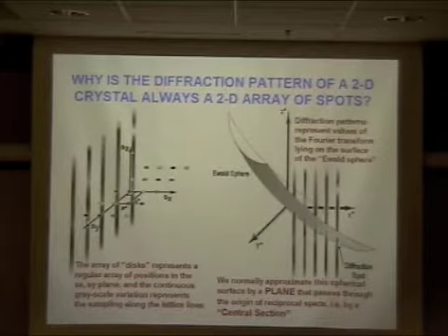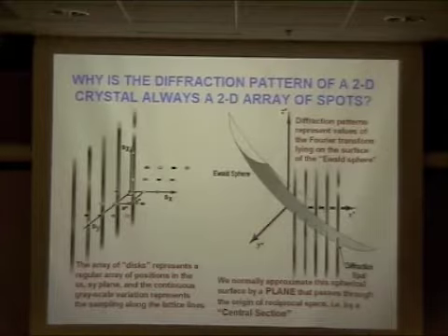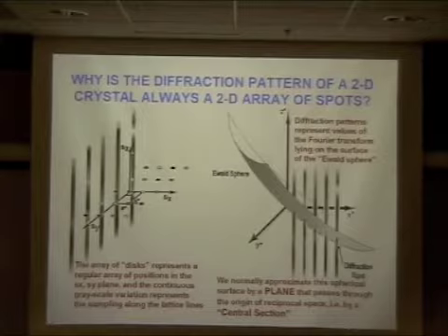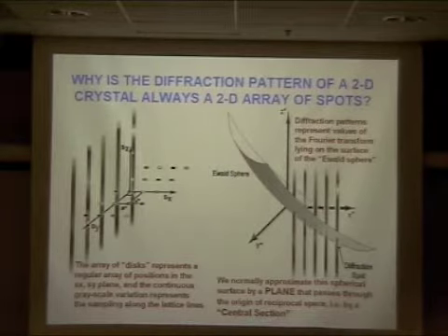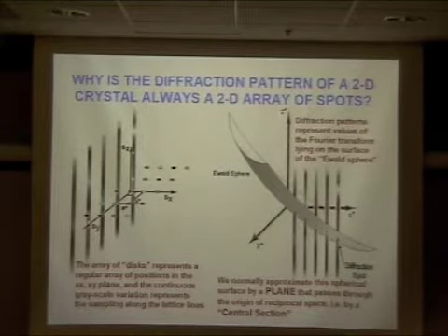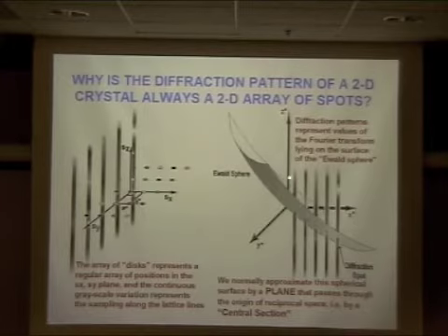Normally, you don't have to worry about it, but when you get to really high resolution, and if your crystal is somewhat thick, you have to worry about the fact that electron microscope images are not absolutely perfectly described as being projections. As a result, we have to generalize the projection theorem to say what happens if it's not really a projection. Then we sample not on a plane, but on a spherical surface that is closely approximated by a plane.